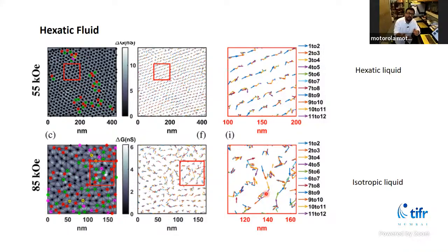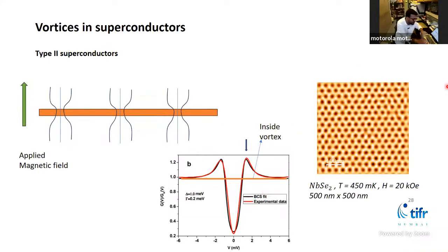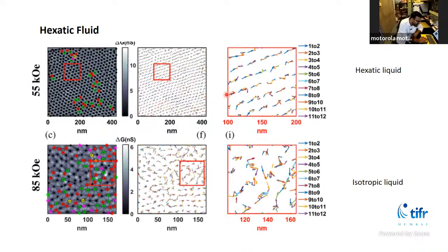Now, what is our lattice here? Our lattice is our vortex lattice that we are studying. And as I have shown you in an earlier slide, it usually forms this hexagonal shape. So in hexatic fluid, it will move only in certain directions. We have three principal directions: one on the horizontal, and the others at 60-degree angles from each other. So you can see in the hexatic phase, they are moving along these directions only, and not like your isotropic liquid phase. So this is one of the cases where we have used STM to study material properties, in this case, vortex material properties. STM has proved to be a very powerful tool to study unusual phases of matter.